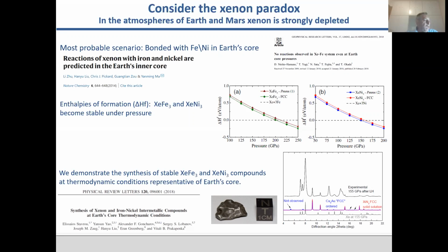However, experimental attempts to synthesize these compounds in 2010 were not successful, although the relevant pressures and temperatures were not exactly close to the Earth core. So we said, okay, we have a theoretical prediction, we have a problem here, we have some previous results, let's see what's happening. Of course, we had to increase the pressure much higher. These are the results of our theoretical predictions. You need at least 200 GPa for iron and 150 GPa for nickel. And we managed to synthesize both compounds, xenon-iron and xenon-nickel, with X-ray and Raman and everything. And this was published in PRL 2018.